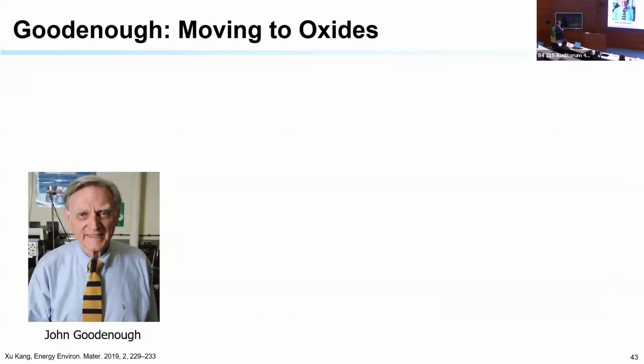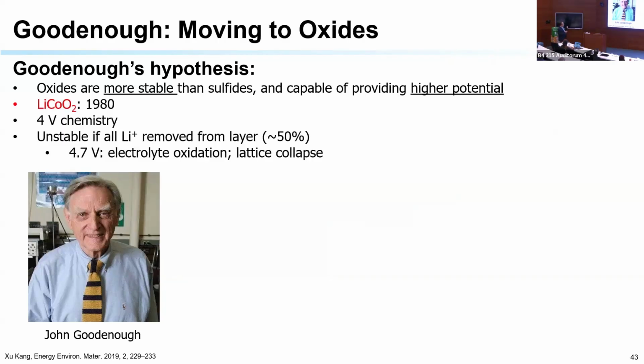And this gentleman, John Goodenough, who lived to be 100, passed away 2 years ago at UT Austin. He said, okay, well, instead of titanium disulfide, we should move to oxides because oxides could give you, he looked at the energy band diagram, he was a physicist, and realized that oxides could give you a higher voltage. So he proposed lithium cobalt oxide in 1980. This is roughly a 4-volt cathode. Actually, this is the cathode used in almost all portable electronics. If you have an iPhone, if you have an iWatch, any of these devices, you are using this material.